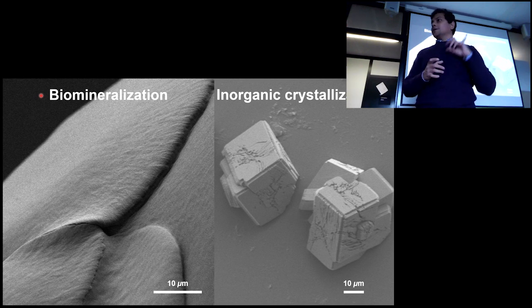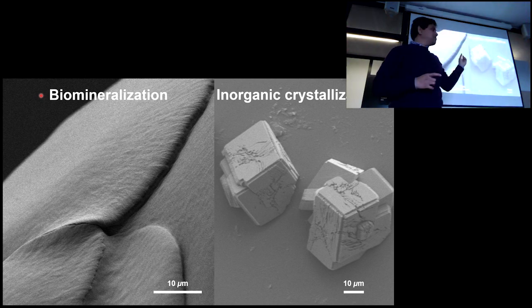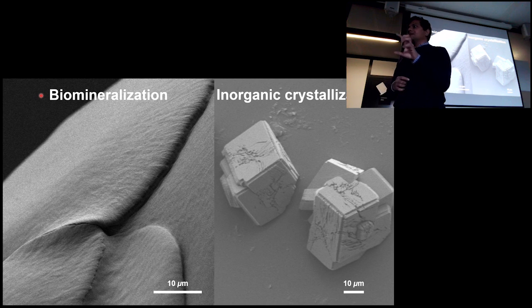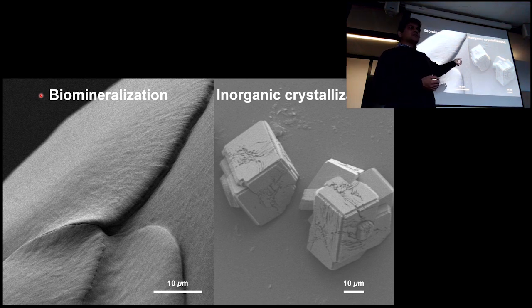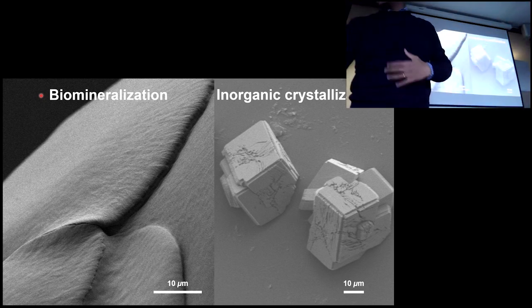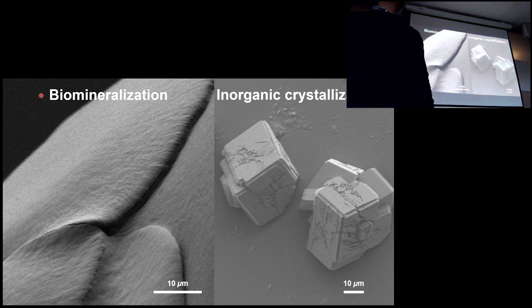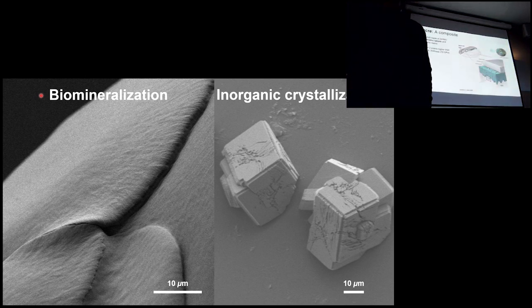So the key here is polyacrylic acid. Actually, interestingly, this whole approach began by using polyacrylic acid as an inhibitor that cannot allow calcium carbonate mineralization to happen. On the other hand, this is what we got. So it just controls the mineralization process rather than stopping it.